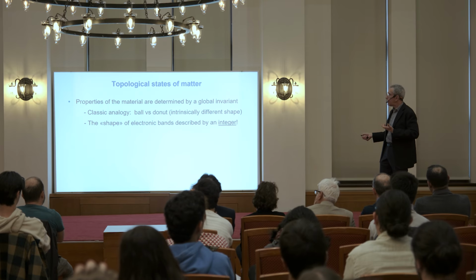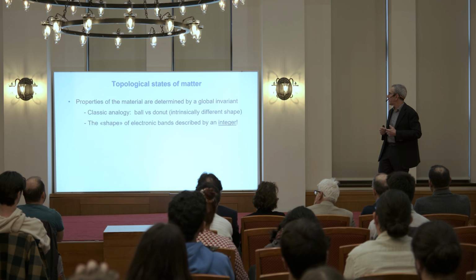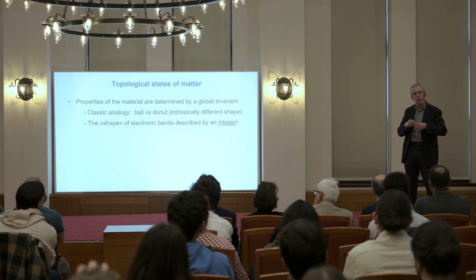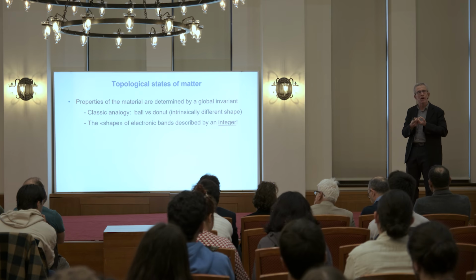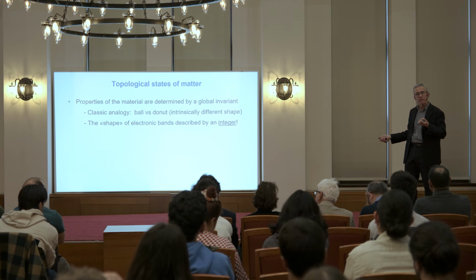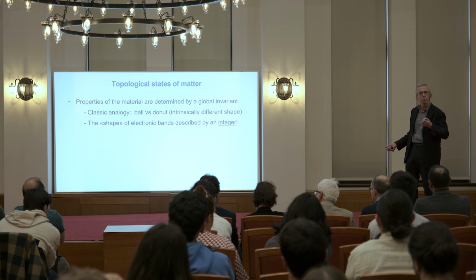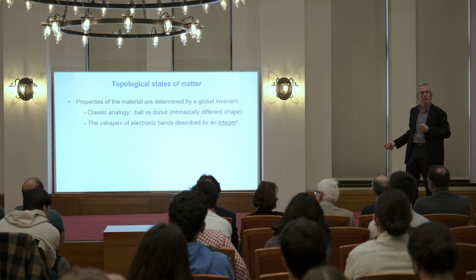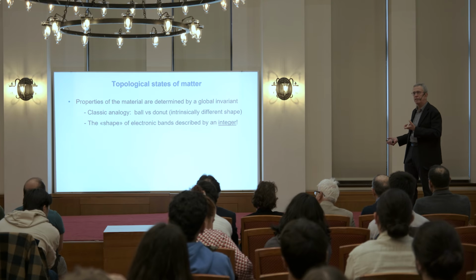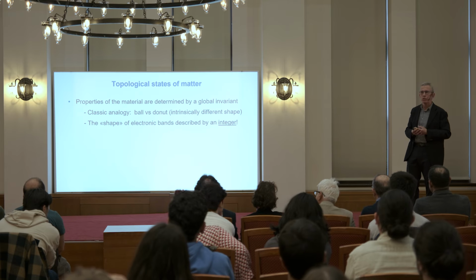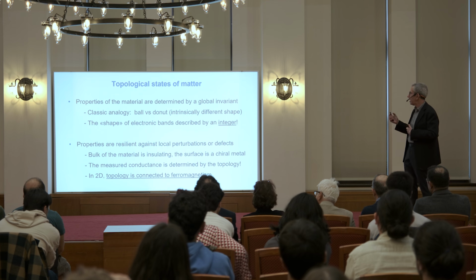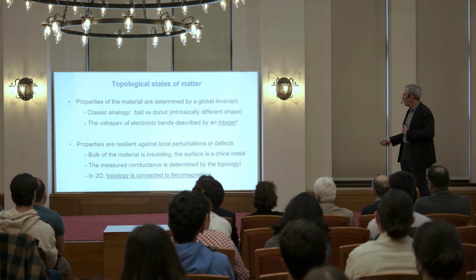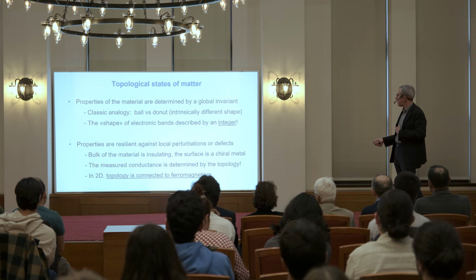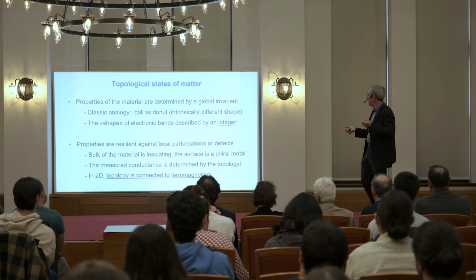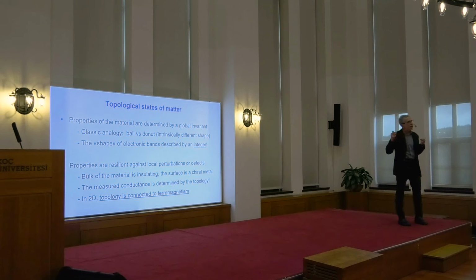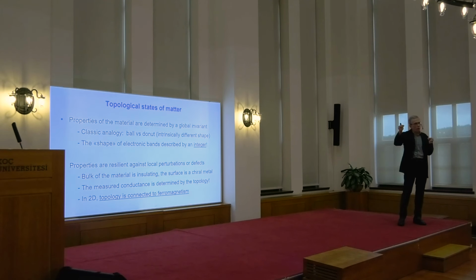So in the case of topological states of matter, the shape of the electronic band is more difficult to visualize. First of all, one needs to look at the nature with which the bands are connected to each other. But what is important is that this shape is described by an integer, that it could be 0, 1, -1, 2, -2, etc. Okay? So it's a property that can be quantified by an integer, and it's a global property of the electrons. That's what is special about topological states of matter. Now, this integer is resilient against local perturbations or defects. And you can see that, right? Because this integer is called a Chern number. It cannot be 0.9. It can be either 1 or 0 or -1.